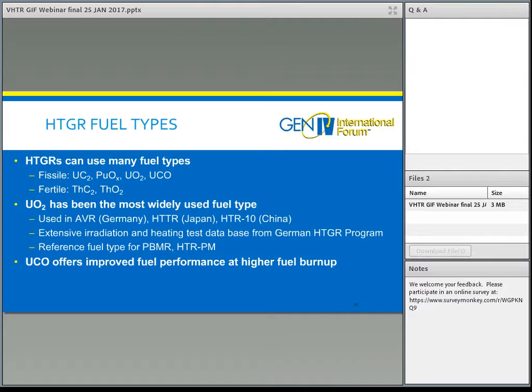The other fuel type that has been getting a lot of attention is uranium oxycarbide. This is made up with a mixture of UO2 and UC, and it has been seen to have much better control of carbon monoxide buildup in the fuel particles, and thus it has a better performance because of less internal pressure in the particles. And as we'll talk about later, one of the key safety features for this type of reactor is keeping the fuel particle at the very smallest level to keep that particle intact.